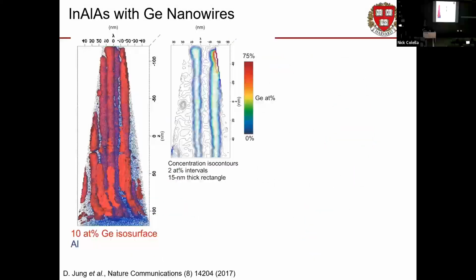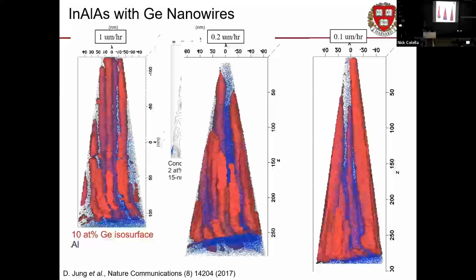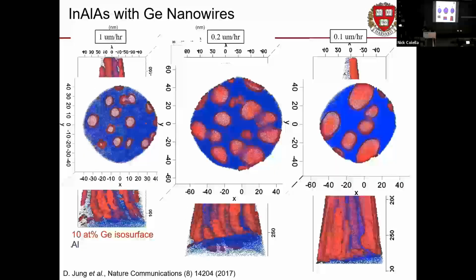This thing I showed you before, these are germanium nanowires grown inside of a 3-5. Again, very hard to do analysis on this. And depending on your growth conditions, you get different shapes, you get different diameters, you get odd effects where the wires start to sort of grow into each other and merge. There's a purely 3D system with all sorts of cool synergistic effects, but you've got no way to analyze it other than atom probe. Works fine.